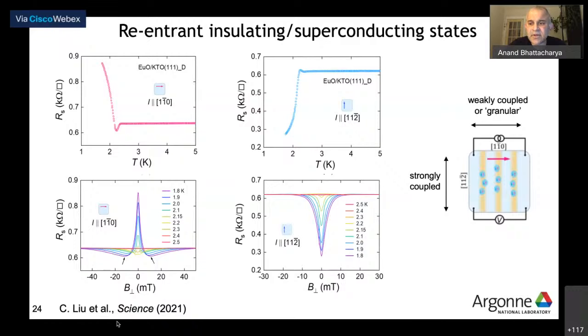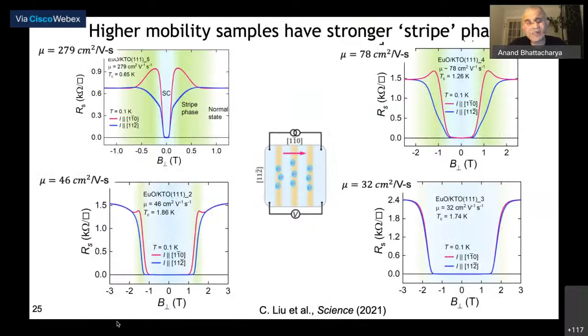Also, even in samples where you measure R versus T and you don't see much at all of this stripe, this anisotropic phase, if you turn on magnetic fields, it can amplify that effect. You saw the top left-hand data already. As you go to lower and lower mobilities, the anisotropy is not as strong, but it's there. You can reveal it by applying a magnetic field at low temperatures, like at 0.1 Kelvin.